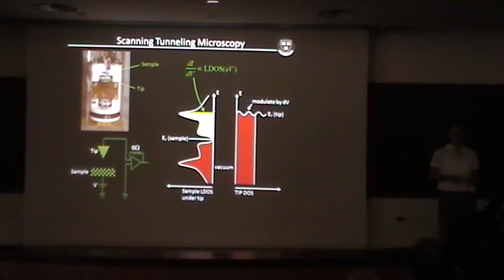There's a paper by the Davis group in which they measured the energy of the boson modes, then did some kind of O16, O17 substitution, measured them again, and then went back to O16, and they could show that the frequency of the boson modes was shifting slightly with the isotope.